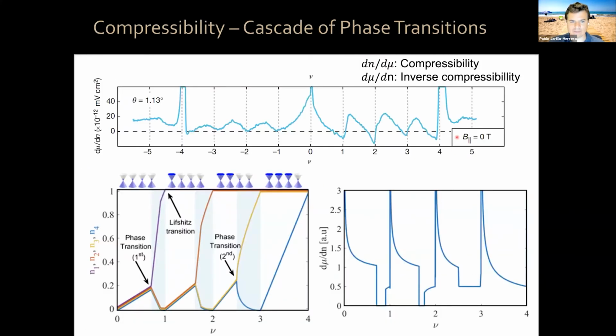Let me show you here, zooming in some of the data at 1.13 degrees, okay? You see that at each integer you have a feature, a sawtooth-like behavior. Turns out, to 0th order, you can understand this feature in the inverse compressibility that occurs at each integer as spontaneous flavor polarization. And by flavor, I mean spin or valley, okay? Remember the spin and valley degrees of freedom of the system, due to strong electron-electron interactions.